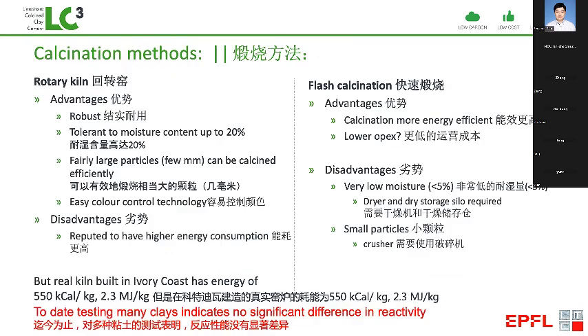And to do this processing, you can use a rotary kiln, you can use flash calcination. Both have different advantages and disadvantages, but we see really very negligible impact on reactivity. And you can even adapt an existing clinker kiln. So we know in China you have a lot of old kilns. These can easily be adapted to calcining clay rather than having to be demolished, which is, of course, a waste of resources. We have even been able to make calcined clay in a clinker kiln only 6 hours after stopping production of clinker. But of course, in the long term, it's better to adapt the burner to have lower temperatures.